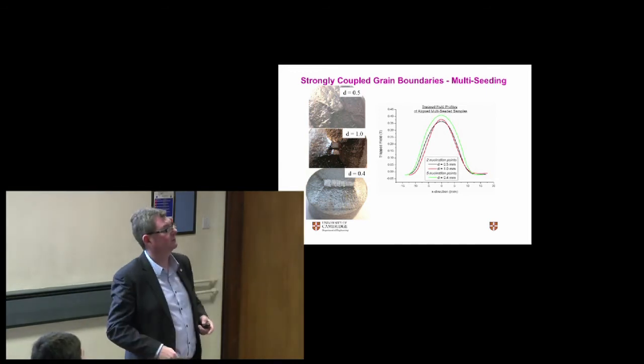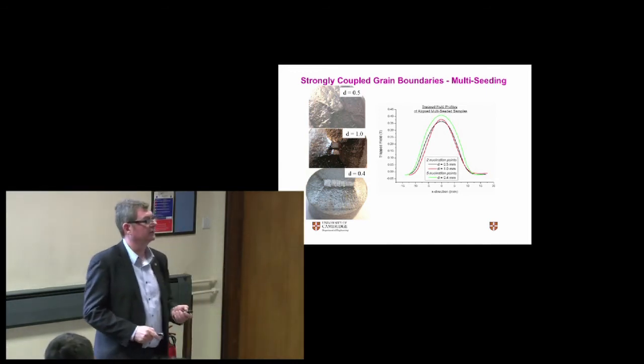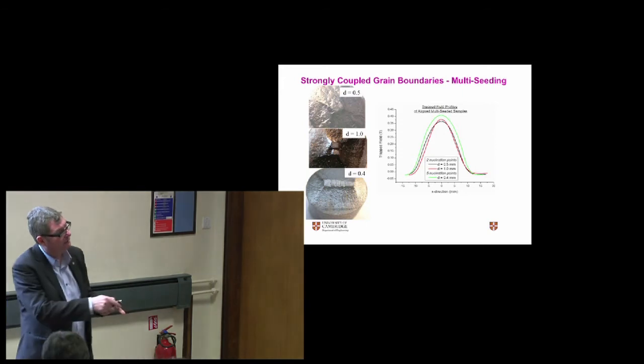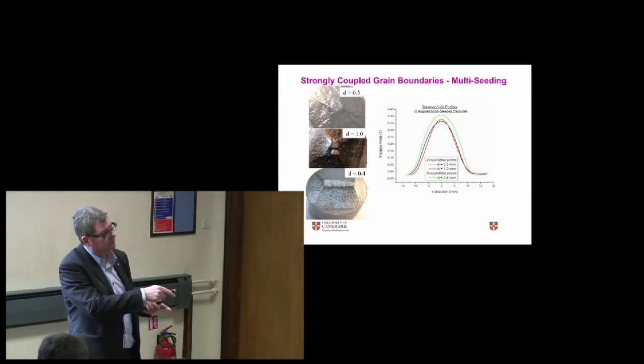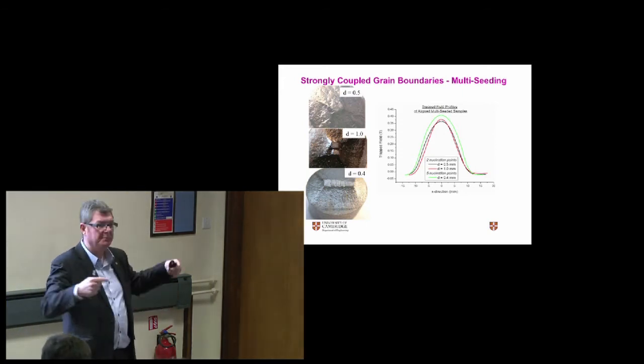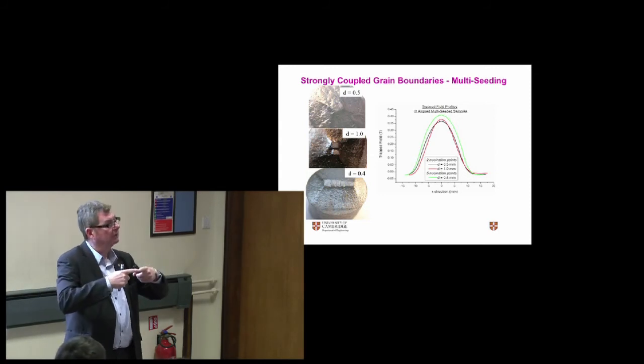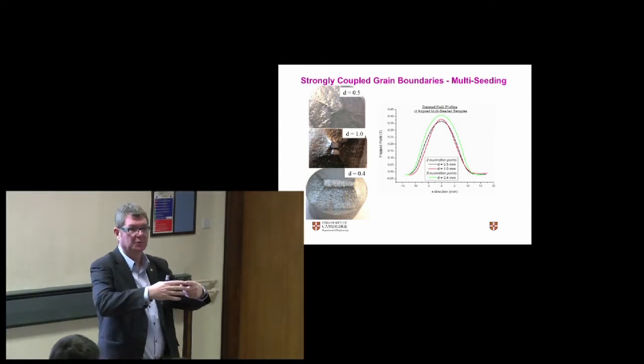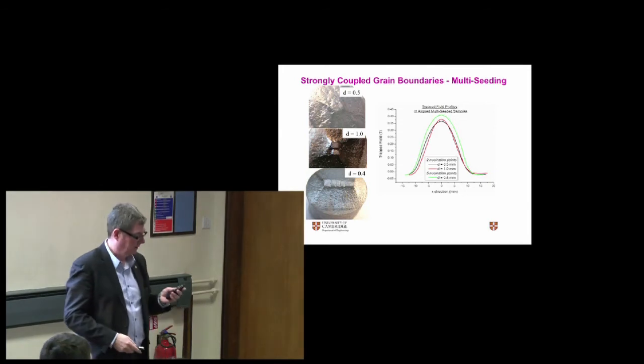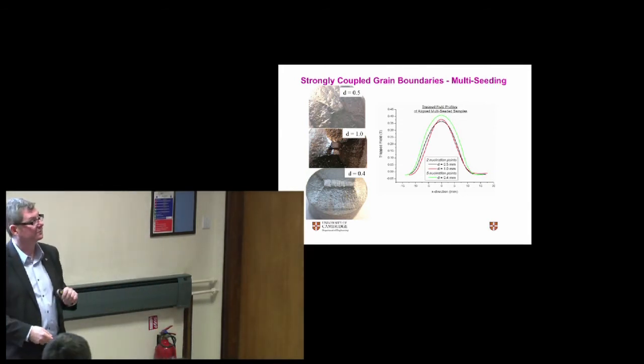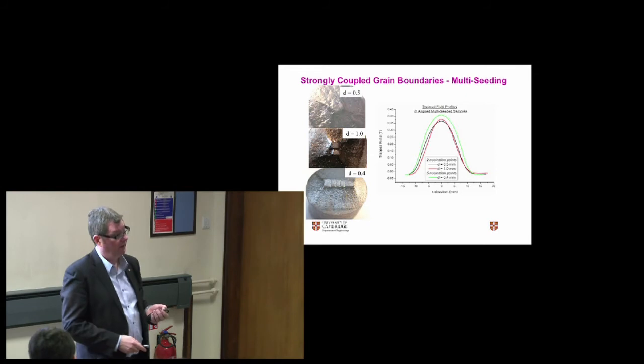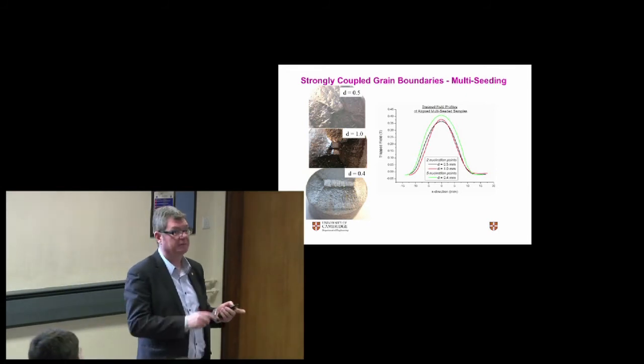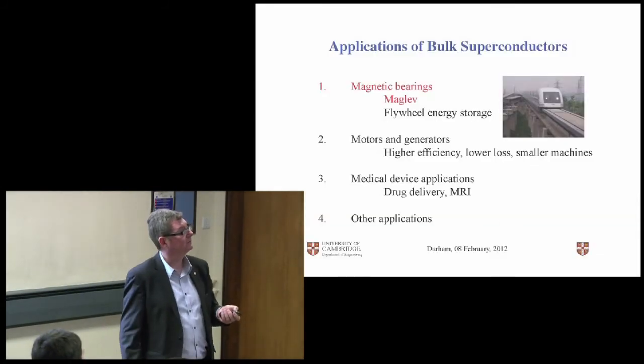Obviously, if you don't have a bridge-shaped seed, it's difficult to control the orientation. We're doing some experiments now where we rotate one of these samples through 45 degrees. So when the grain boundaries impinge, they do so at an angle, and if there are any impurities, they're pushed away rather than trapped at the grain boundary. We just saw these samples last week, and already the results look extremely good. So maybe we've got a way of engineering these grain boundaries.